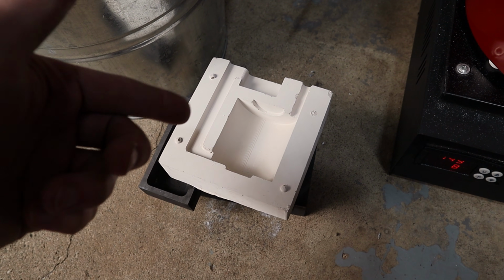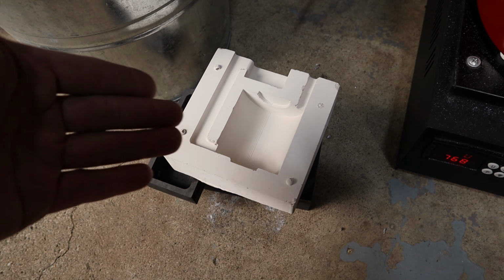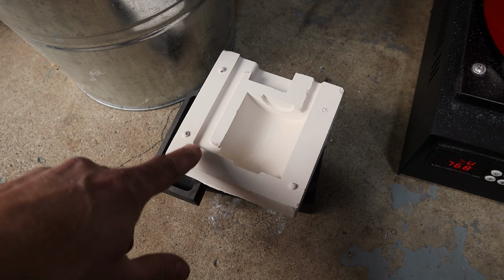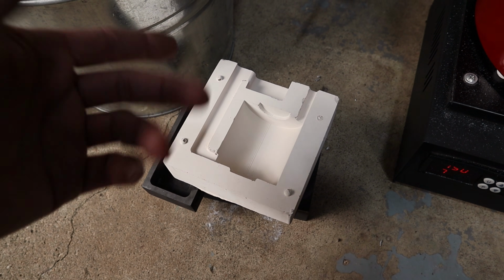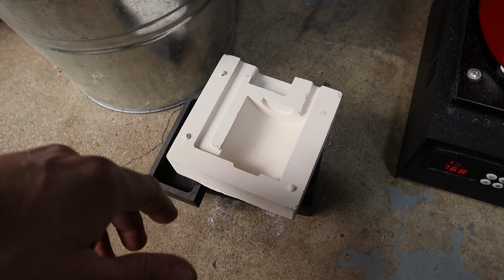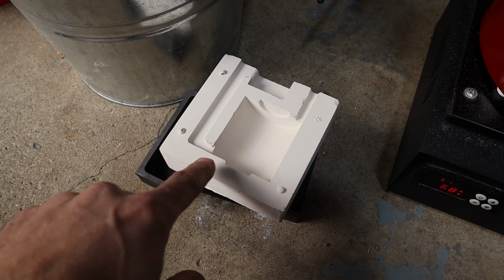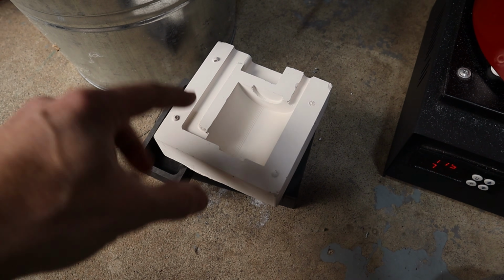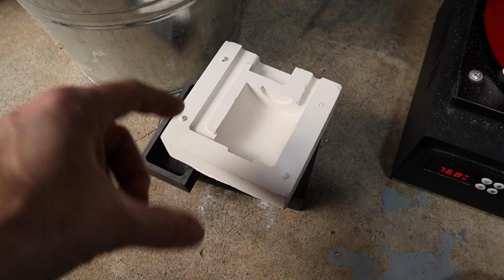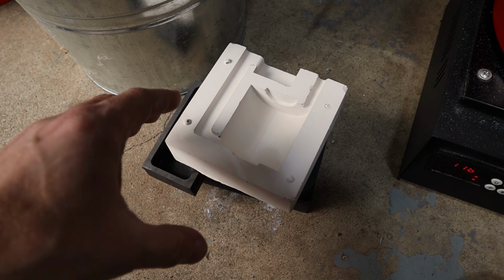One of the drawbacks though is that it takes quite a while to dry this out completely, and that's in part because I didn't really let it dry out naturally. So I was trying to speed up the process just by putting it in the oven for a high temperature for quite a while. One of the issues with this type of system is that there's a lot of moisture that went into creating this. We want to make sure we get as much of that out of there as possible.